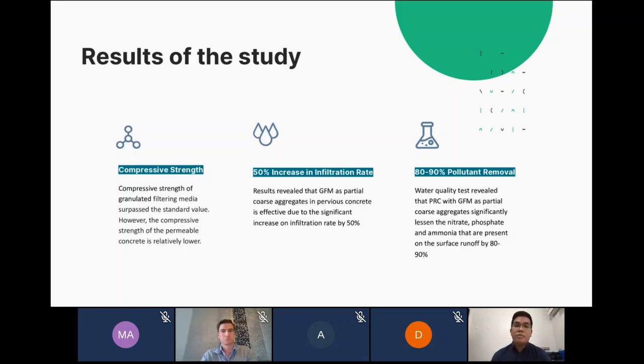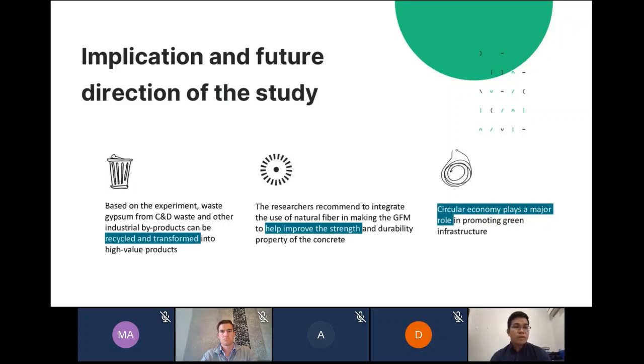And third, in terms of pollutant removal, based on the water quality test conducted, it revealed that the permeable reactive concrete with granulated filtering media as partial coarse aggregates significantly lessens the nitrate, phosphate, and ammonia that are present in the surface runoff by around 80 to 90%.